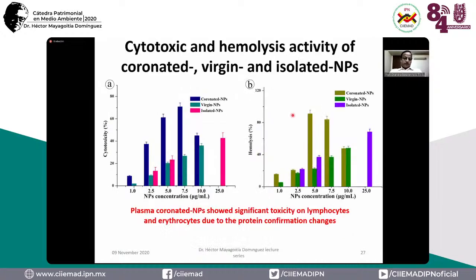And this is the cytotoxic and hemolysis activity of coronated, virgin and isolated nanoplastics. Isolated means we isolated them from face cream and other consumer products. We could see a cytotoxic effect compared to the control, and hemolysis also happening in the case of virgin and isolated nanoplastics. That means plasma coronated nanoplastic showed significant toxicity on lymphocytes and erythrocytes due to the protein conformation changes.